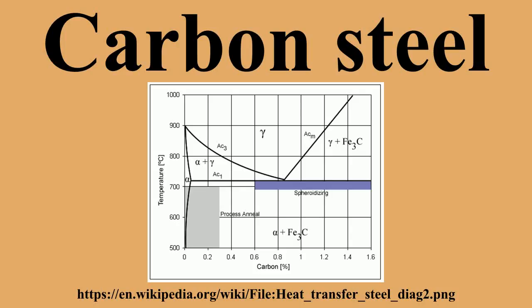Normalizing. Carbon steel is heated to approximately 55 degrees Celsius above AC3 or ACM for 1 hour. This ensures the steel completely transforms to austenite. The steel is then air-cooled, which is a cooling rate of approximately 38 degrees Celsius per minute. This results in a fine pearlitic structure and a more uniform structure. Normalized steel has a higher strength than annealed steel. It has a relatively high strength and hardness.